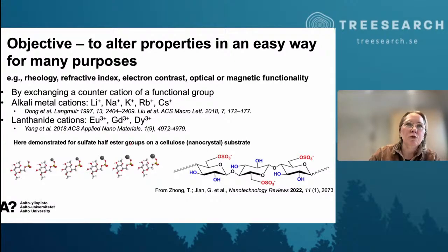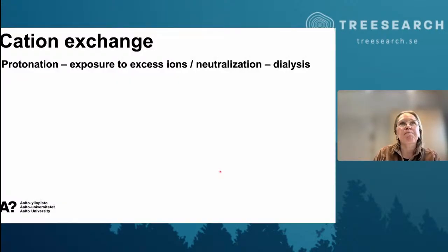So we are focused on the sulfated systems and introducing the cation to that. The procedure is to protonate, then expose the substrate to an excess of the target ions or the cations, neutralize and dialyze, and then analyze how much of the cations we were able to introduce.